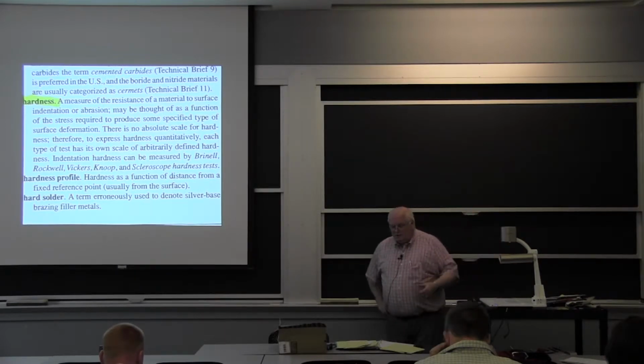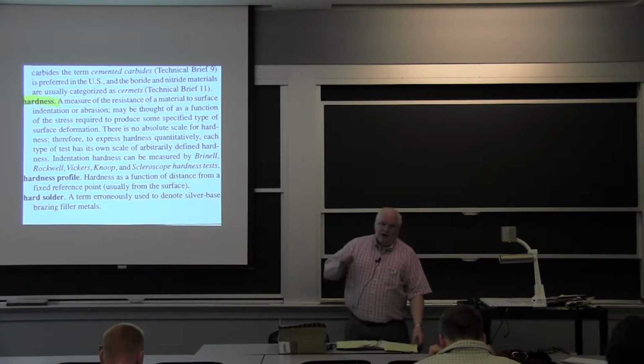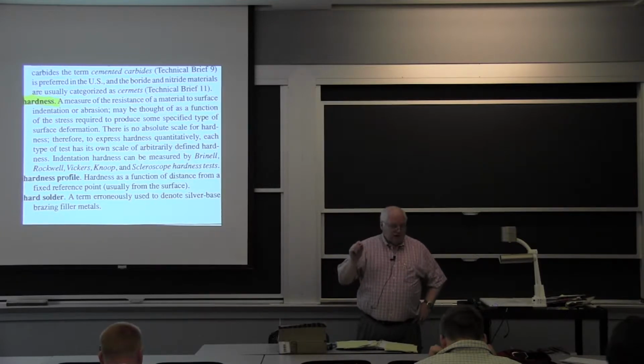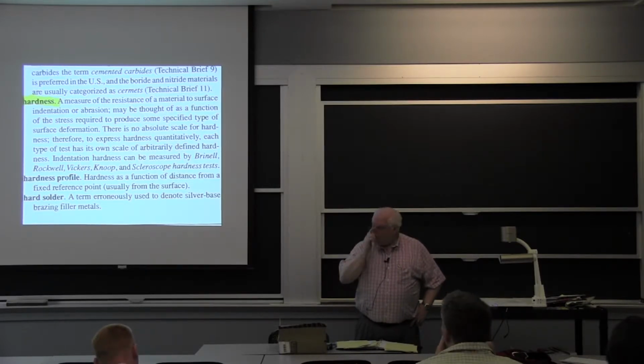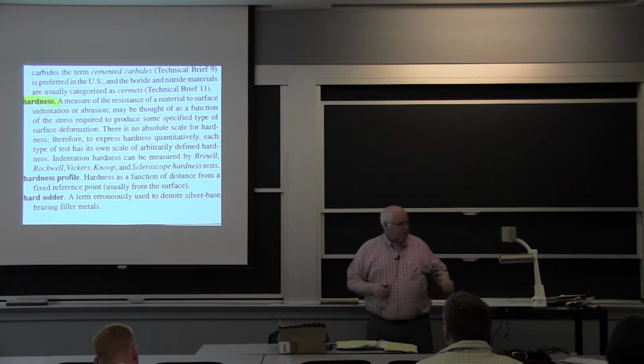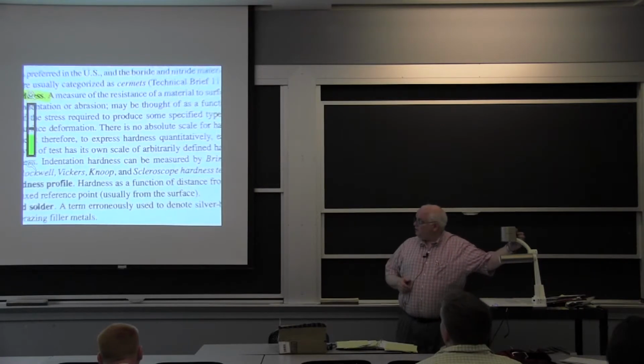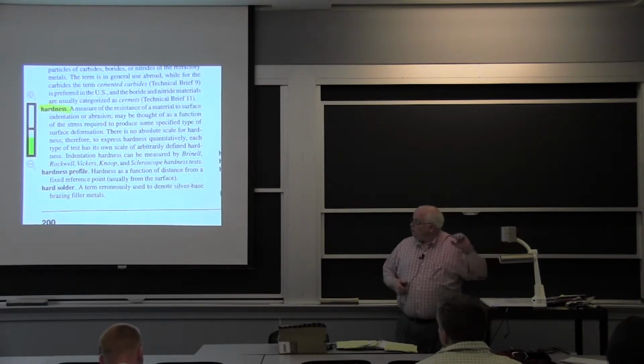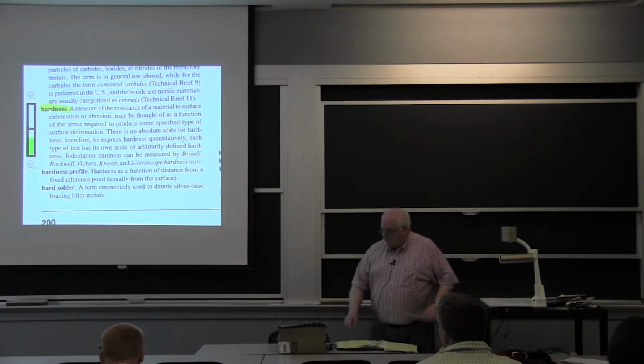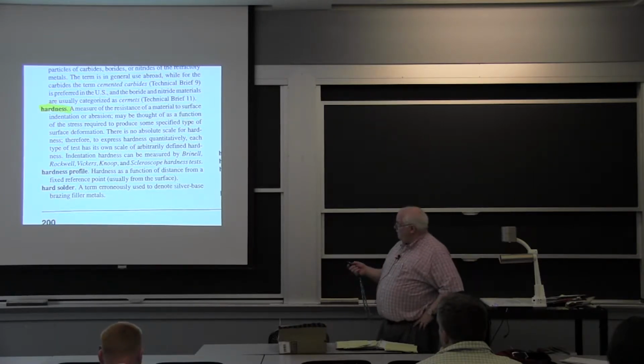It turns out some of the tests are actually 1/3 or 3 times the tensile strength. If you take my deformation processing course, you can prove it mathematically that in a non-plastic, non-work hardening material, it should be exactly 2.57 times, but because it work hardens, it's about 3.